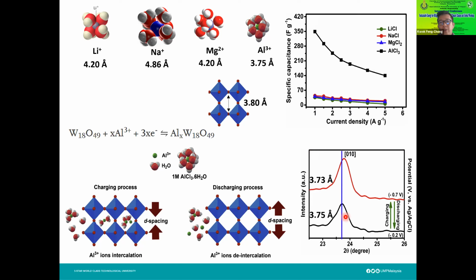So we use the in situ XRD, whereby we come up with the mechanism for the charge storage for this tungsten oxide. When the aluminum ion goes in, there's a contraction of this crystal structure, but when the aluminum comes out, there's expansion. So we can prove that the aluminum ion can go into the crystal structure of this tungsten oxide.